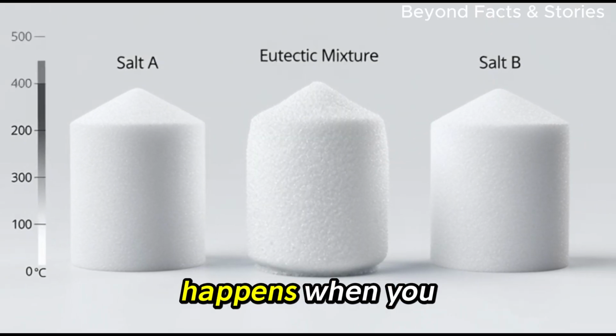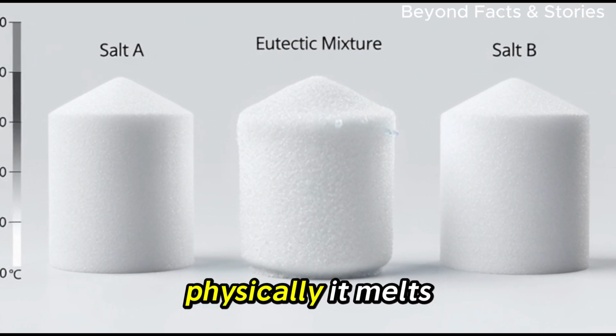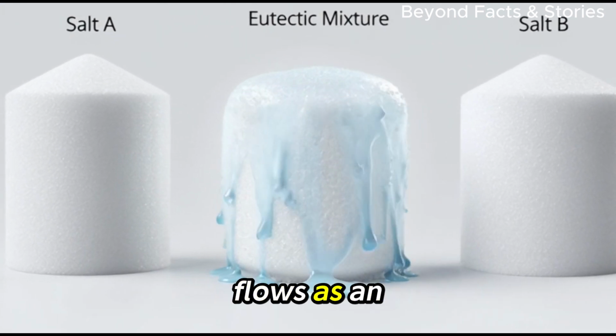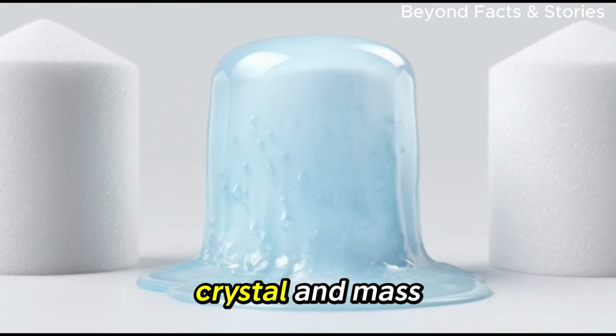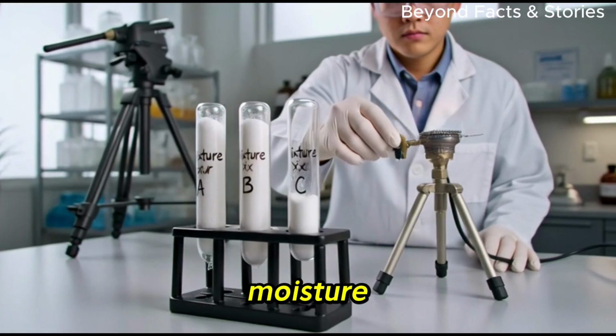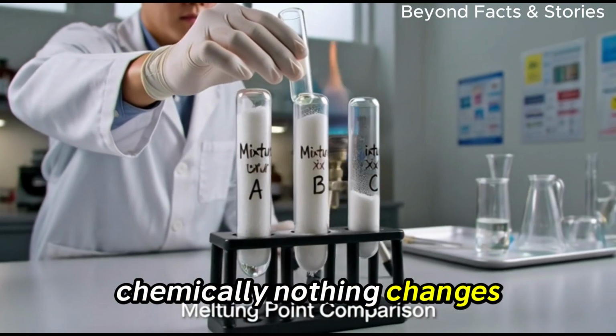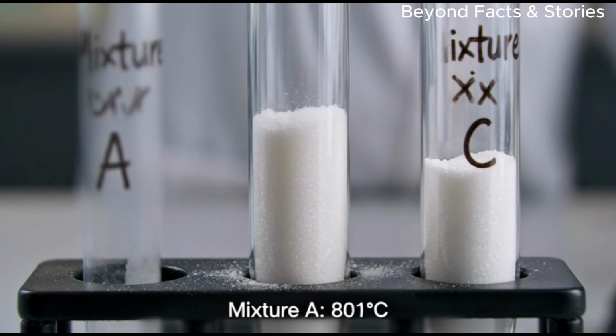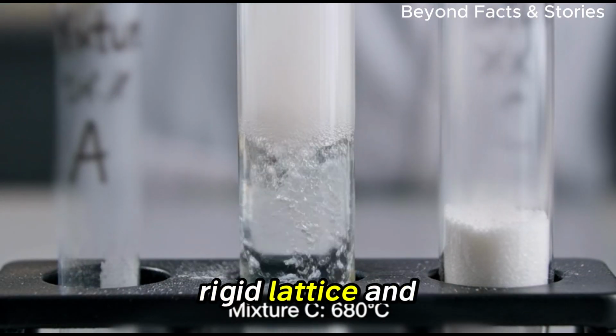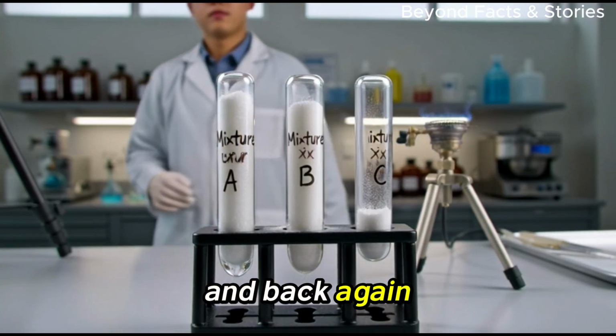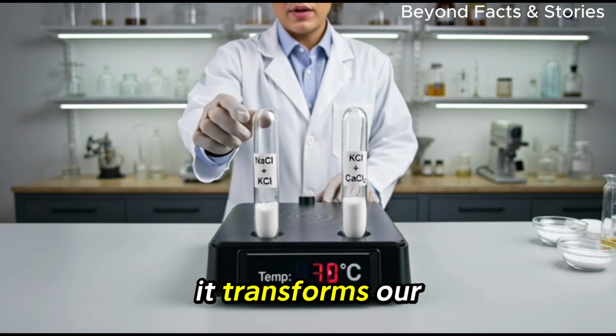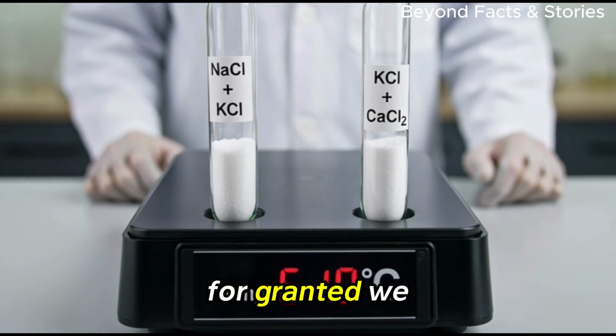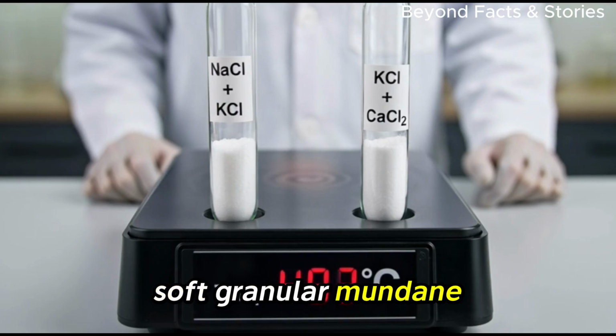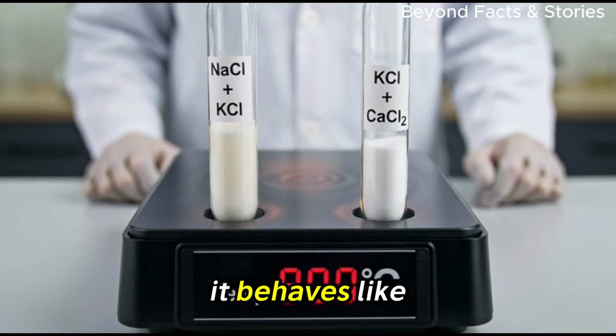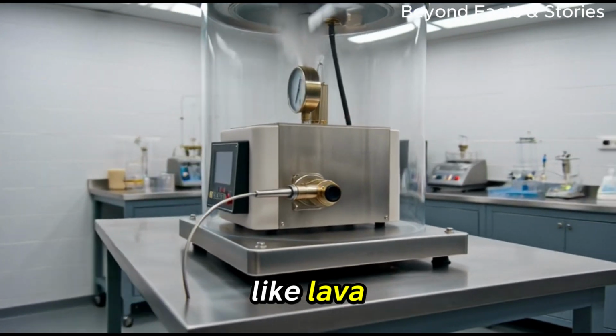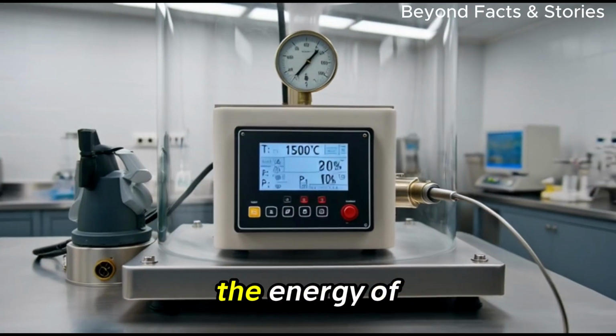So what truly happens when you cast salt like metal? Physically, it melts at extreme temperatures, flows as an ionic liquid, solidifies into a brittle crystalline mass, and remains vulnerable to impact and moisture. Chemically, nothing changes, it remains sodium chloride. Structurally, it transitions between rigid lattice and mobile ionic liquid and back again. But philosophically, it transforms our perception. We take salt for granted. We see it as soft, granular, mundane. Yet under the right conditions, it behaves like molten rock. Like lava, like industrial material capable of storing the energy of the sun.